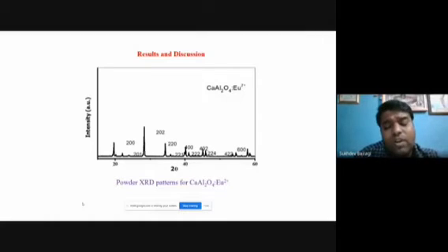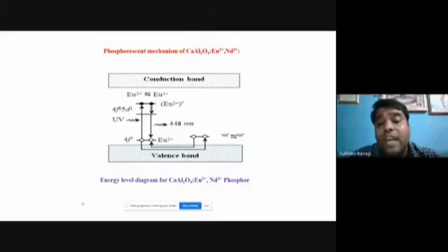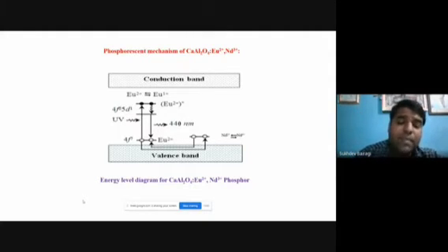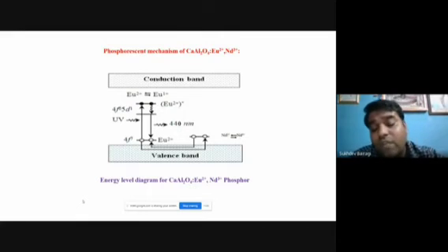The small amount of doped rare earth ions has almost no effect on the calcium aluminate. The appropriate phase composition was observed without loss of crystallinity in the phase. The phosphorescent mechanism of the calcium aluminate doped with europium and co-doped with neodymium, we can see, the mechanism of the long afterglow due to the trap-transport process can be suggested as shown in the figure. When the source lamp was switched off, the intensity of the persistent emission decreased rapidly and finally formed a long persistent emission for several tens of minutes.